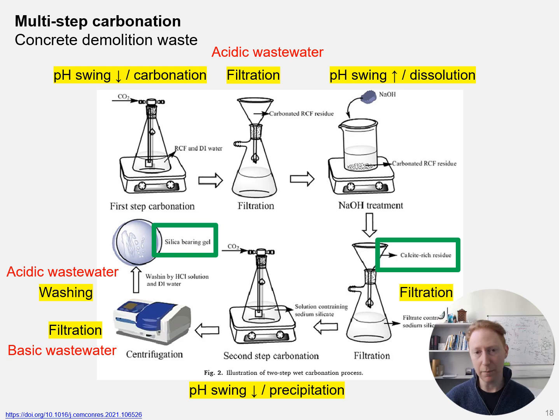For the multi-step carbonation process, I've taken a couple of examples. For the first example, which is shown here, for concrete demolition waste, we need to first separate the aggregate from the cement paste, since the cement paste is the material that contains the uncarbonated calcium and which is carbonated. This material is immersed in water, it is exposed to CO₂ gas, and then the carbonated material is filtered. The filtered solid material is then put into a NaOH treatment stage where there is a pH swing back up to basic conditions, which causes the silica to dissolve.